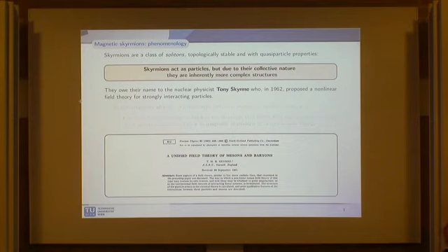So what are skyrmions in general, which is a more general concept with respect to magnetic skyrmions. Let's start from skyrmions. These are defined as a class of solitons, which means that in some sense they behave like waves: they have some shape which carries some energy, and the shape of this wave packet does not change in time. Then they are topologically stable, meaning that although this configuration may not globally minimize the magnetic energy functional, still it is the minimizer in some homotopy class.